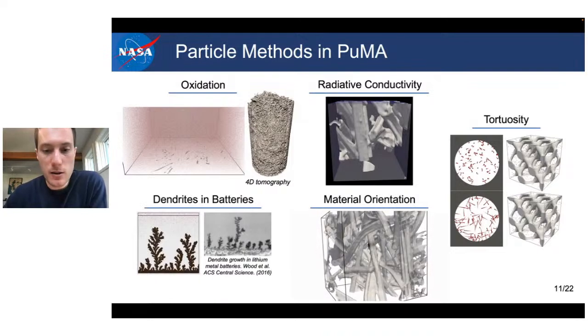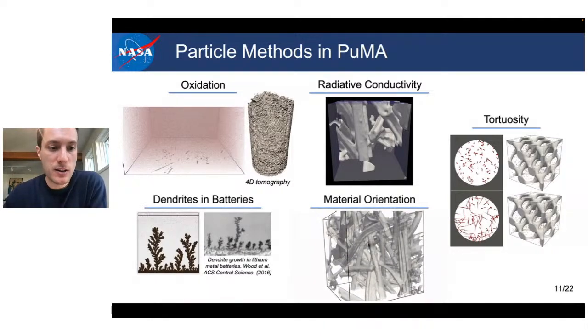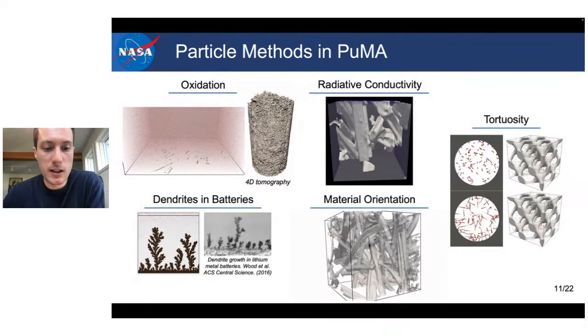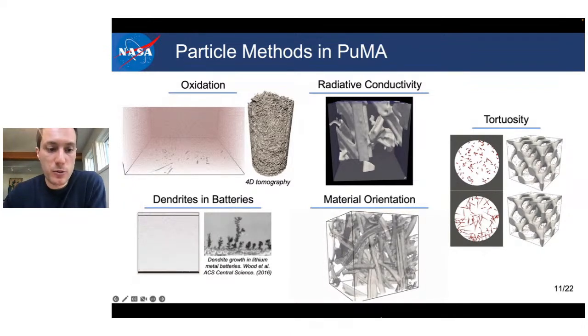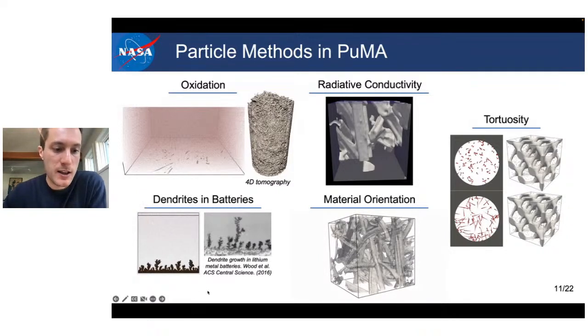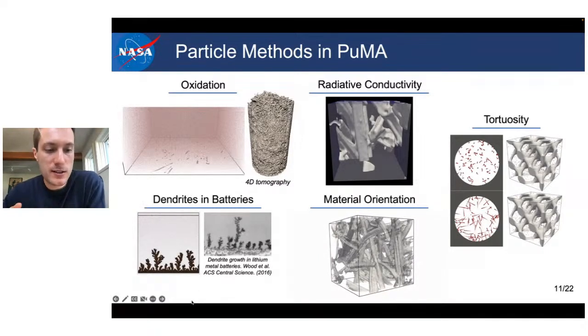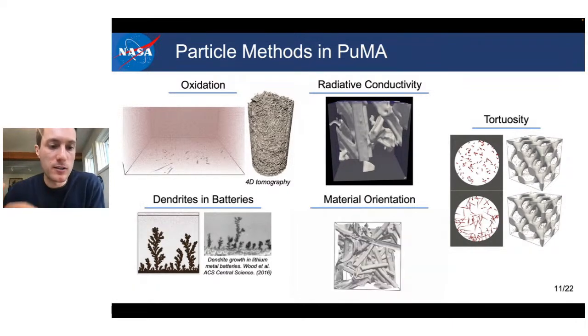And an even more recent application is the dendrite growth in lithium metal batteries. We have used the Puma particle method to do the opposite type of phenomenon than oxidation, where you're actually depositing particles as you go. And by tweaking again this sticking probability, we have shown that we can mimic a similar dendrite growth as in real lithium metal batteries.